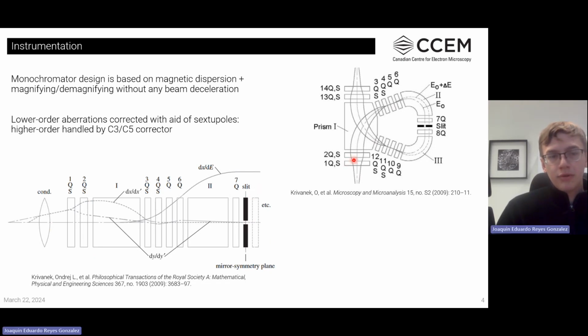Inside of this monochromator, we have a series of sextupoles as well that are positioned at the start and the end of our monochromator. These are just to help with some of the lower order aberrations that are induced by these magnetic lenses, but we can handle the higher order aberrations using our C3, C5 corrector that's a bit further down the line.